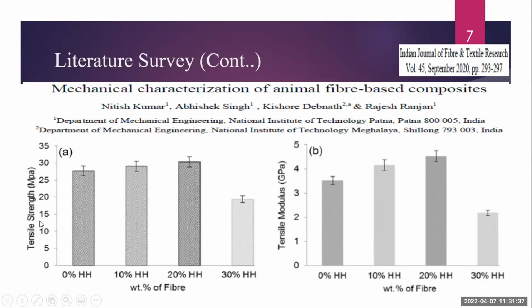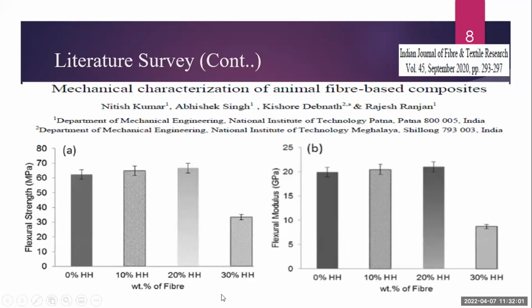It means the tensile strength is highest at a mixing ratio of 20% horsehair with 80% polylactic acid by weight percentage. Again, the same result can be seen in the tensile modulus, which is also good for 20% horsehair and 80% polylactic acid. They also tested flexural strength, and they found that the sample of 20% horsehair and 80% polylactic acid gives the best result compared to pure polylactic acid or any other mixing of horsehair with polylactic acid. The flexural modulus gives the same result as the flexural strength: the ratio of 20% horsehair with 80% polylactic acid gives the best results.